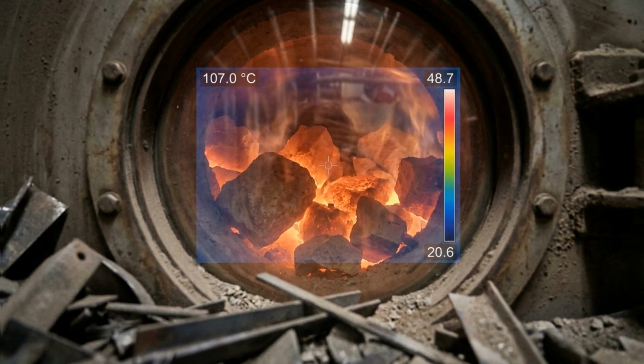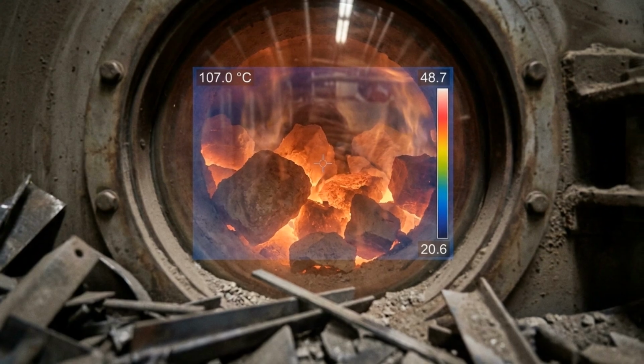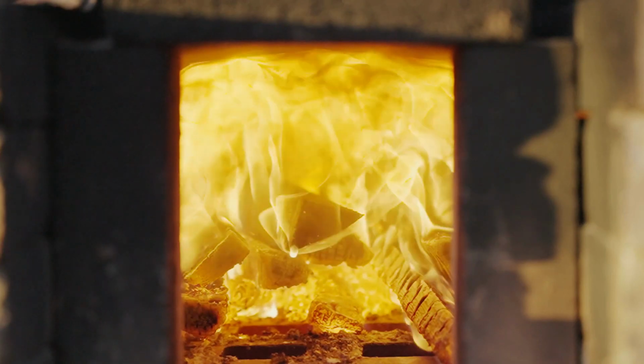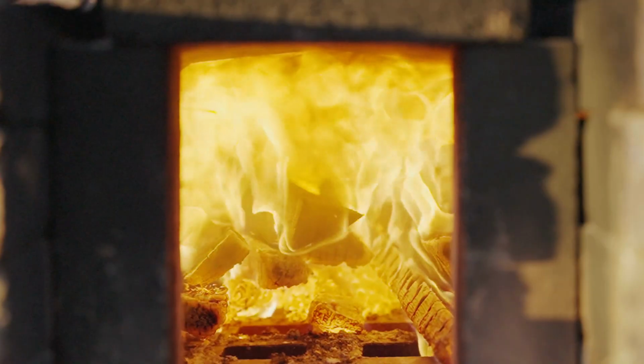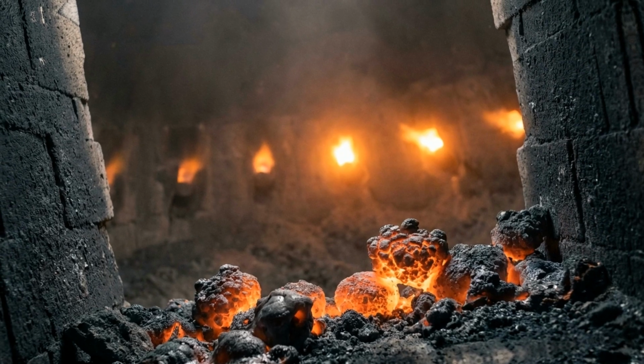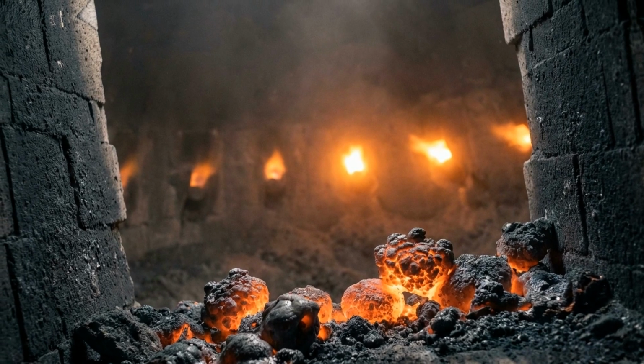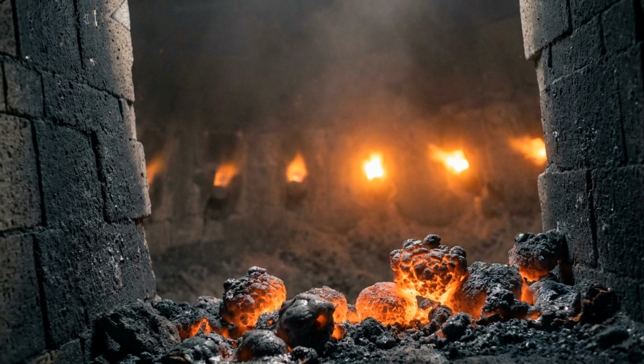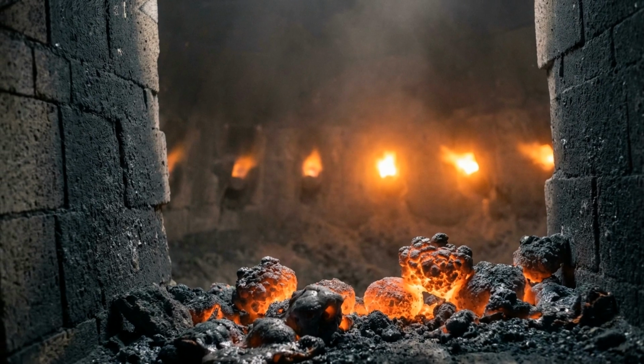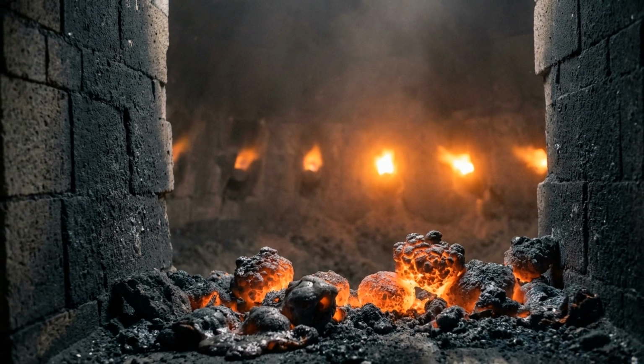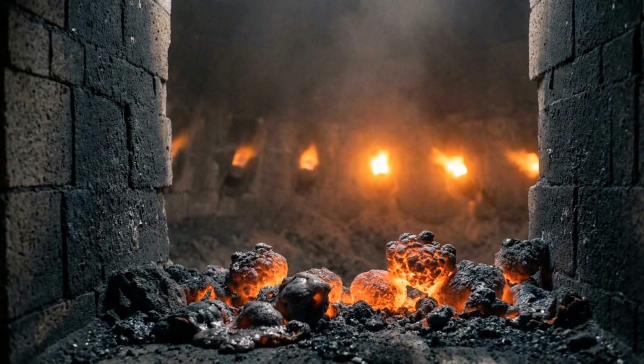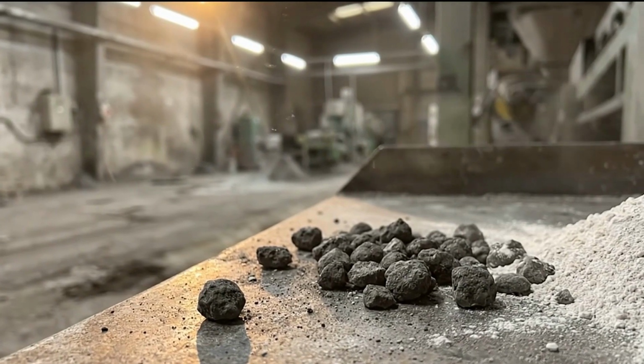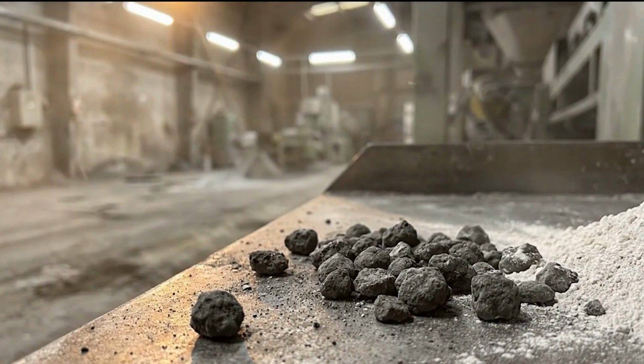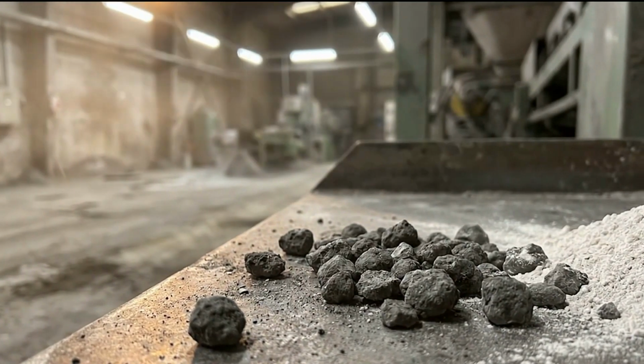At around 800 degrees Celsius, the limestone begins to decompose. Calcium carbonate breaks down into calcium oxide and carbon dioxide, a process called calcination. The carbon dioxide is driven off as gas. The calcium oxide continues toward the burning zone, where temperatures reach 1400 degrees Celsius or above, and the material partially melts and fuses into nodules called clinker. Clinker is the intermediate product of cement manufacture. It's dark gray, hard, and looks roughly like gravel. Ground up and mixed with gypsum, it becomes Portland cement.